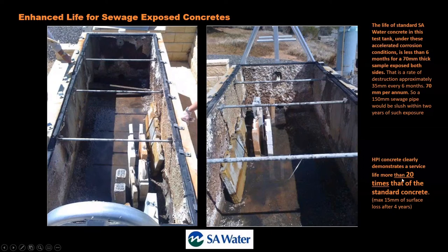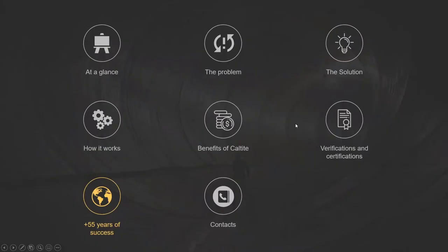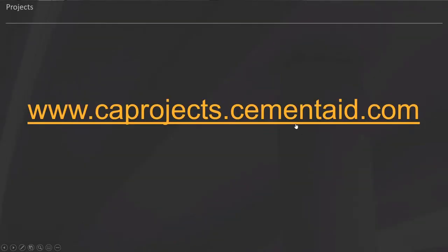The HPI concrete clearly demonstrates a service life of 20 times that of standard concrete. There's a maximum 15 millimeters of surface loss, and that's at the worst end where the hydrogen sulfide gas goes in. So something like 15 millimeters of loss after 4 years, as opposed to normal concrete with 70 millimeters being completely destroyed in 6 months. We'll have a look at some actual projects now.